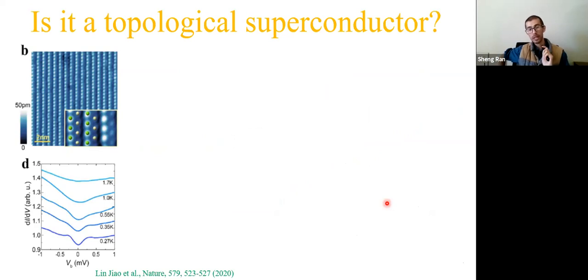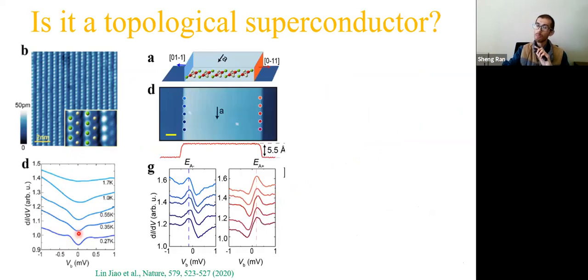So we did an STM study in the collaboration, and here I'm showing the STM study when they put the tip in the bulk. When they put the tip in the bulk, you can see the gap indicating the superconducting energy gap. But they can also put the tip at the edge of the sample. It's a layered sample, with different layers. They can put the tip at the edge of the layers. When they did this, depending on which edge they put the tip on, you see this anti-symmetric in-gap state. These are still within the superconducting state.